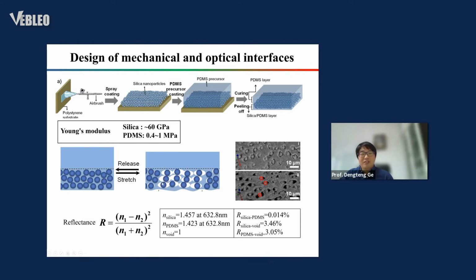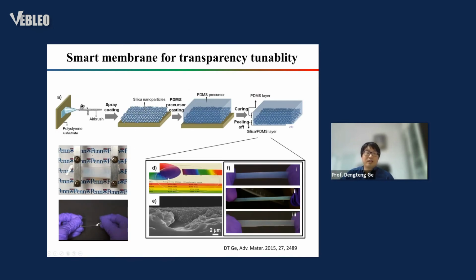So this void will be caused, like a PDMS void and a silica void. They have a new interface, a light scattering interface. So they can form a transparency change. So here is the composite membrane. When we prepare this one, it's totally transparent. When we stretch it, it's opaque.